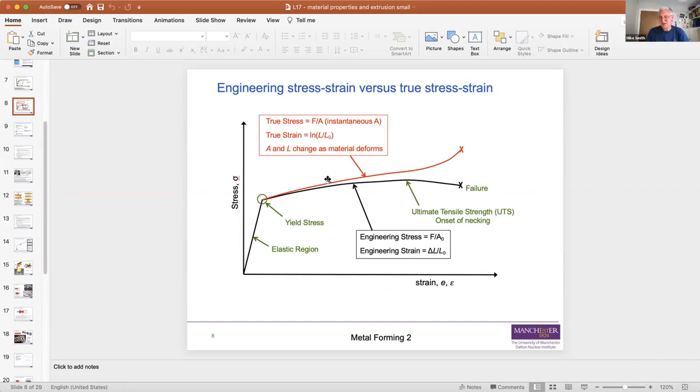Depends on the material. And it depends on the strain range you want to work over. So for a low carbon steel, you would probably take the initial slope. For an aluminium alloy, different materials behave differently. Some have not quite curved work hardening. Some have relatively straight work hardening curves for quite large increments in strain. Then it's pretty obvious that linear hardening is a good model. There are some materials for which linear hardening is not a good model, because the H that you choose is only going to be valid over a small increment in strain. But it's a useful step between the full stress strain curve and elastic perfectly plastic.